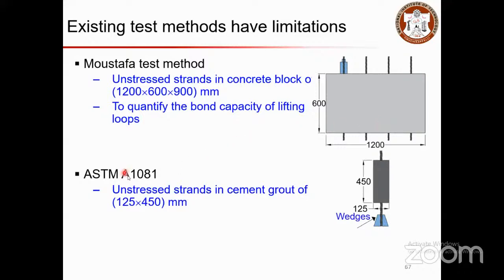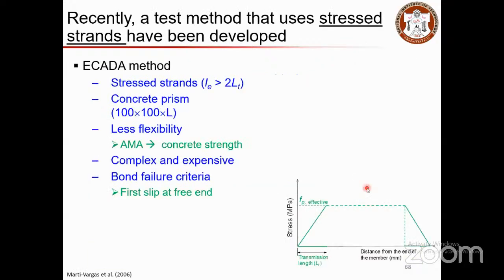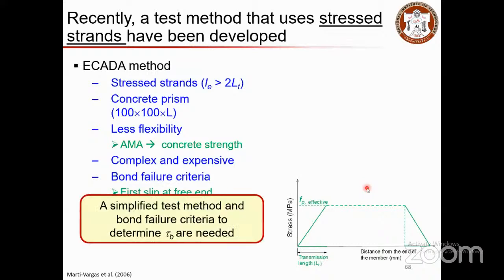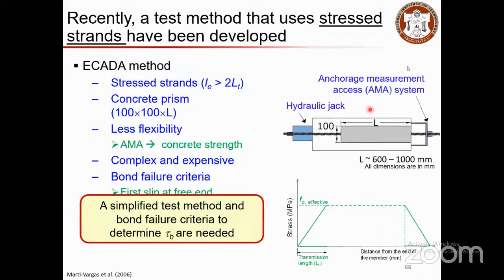And there is a test method ASTM A1081. Again here, the scenario uses unstressed strands in cement grout, and it is also not mimicking the scenario of a pre-tension concrete system. So then the ECADA test method was developed, an anchorage measurement access method. This setup basically replaces the stiffness of the entire remaining length of the specimen. So this involves a lot of complications and is expensive also.